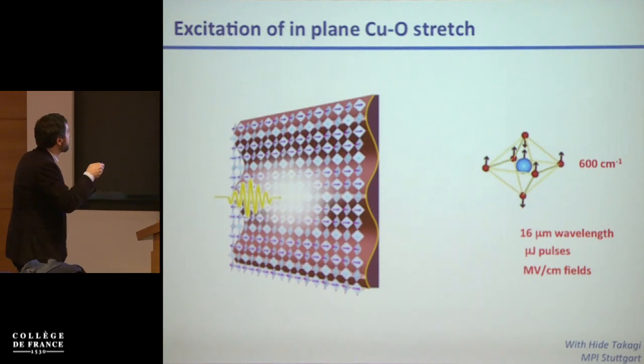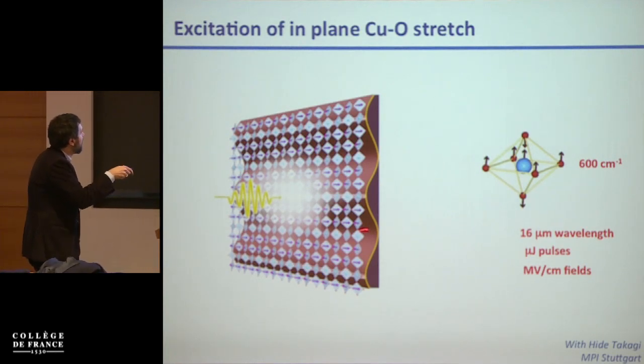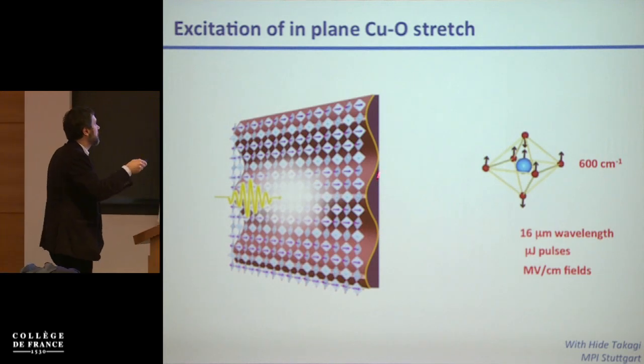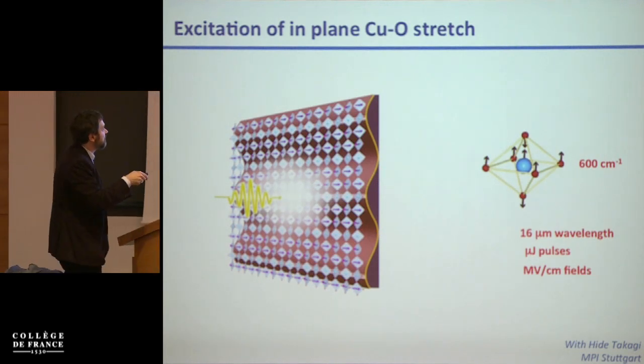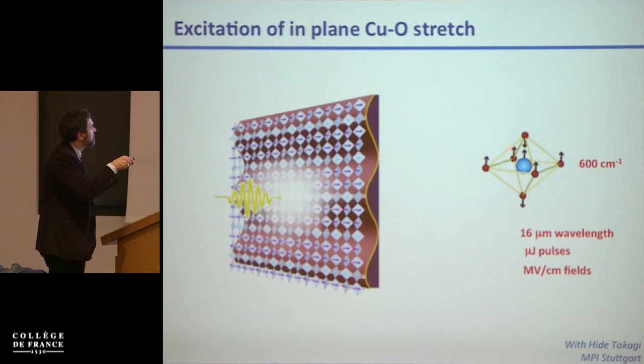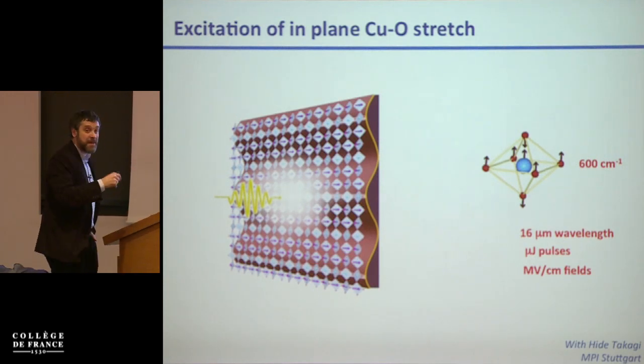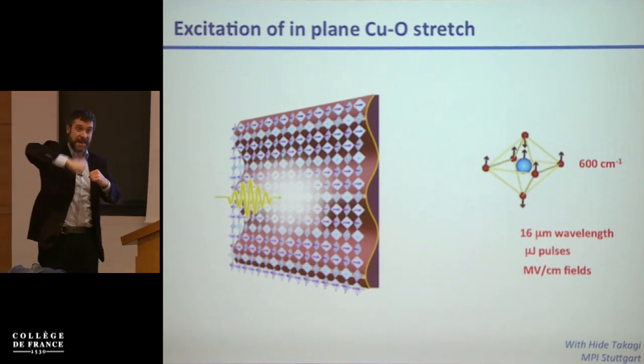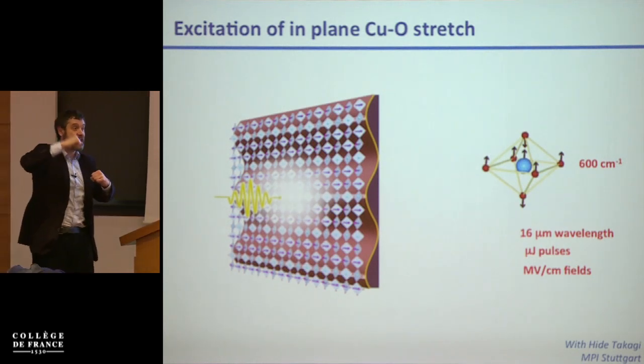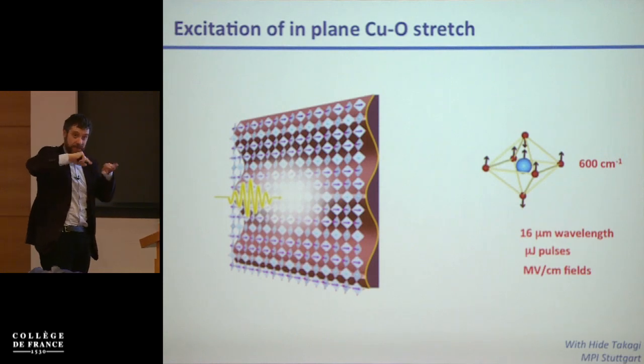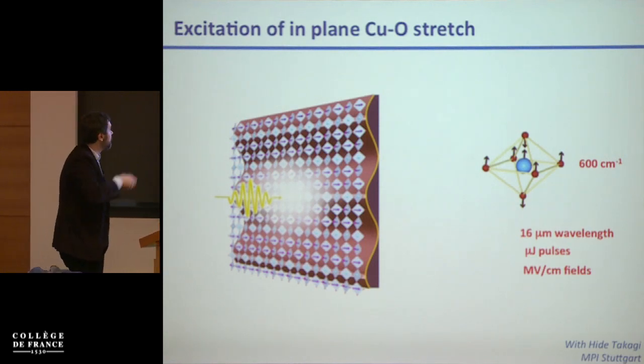Okay? But let's say that we take one of these. This is a cartoon picture of a stripe compound that quenches superconductivity, and we can excite this particular mode at 600 wave numbers with microjoule pulses and many megavolt per centimeter fields. They can now drive this infrared active in-plane distortion in the single layer cuprates and try to melt this.